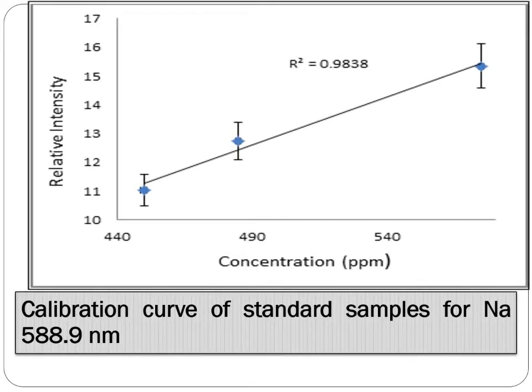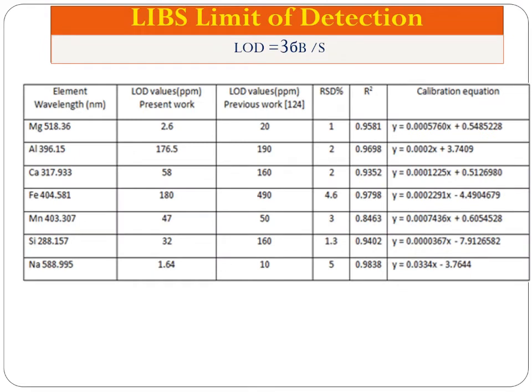This is a calibration curve for sodium at the 588.9 nanometer line, from a concentration of around 440 to around 600 ppm. This summarizes the observed detection limits of the elements available in the examined soil. We have observed a detection limit of 2.6 ppm for magnesium and 1.6 for sodium.